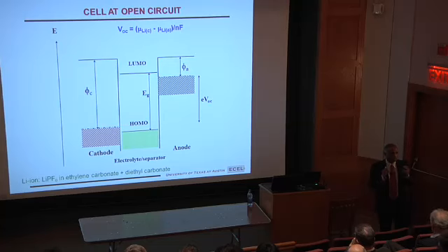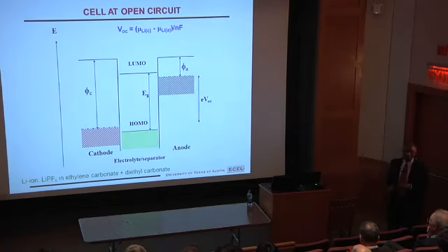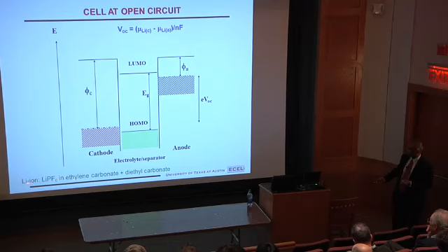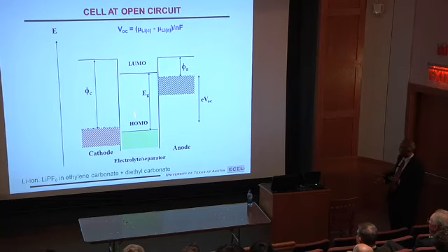That's not good. Electrolyte should allow charge transfer only in the form of ions, not in the form of electrons. So that's what is limiting. When you go to lithium-ion battery, usually in the commercial cell, this is what you use: lithium hexafluorophosphate in some organic solvents like ethylene carbonate and diethyl carbonate or dimethyl carbonate, some mixed solvents to optimize the viscosity as well as the lithium-ion conductivity. So those have much wider window.